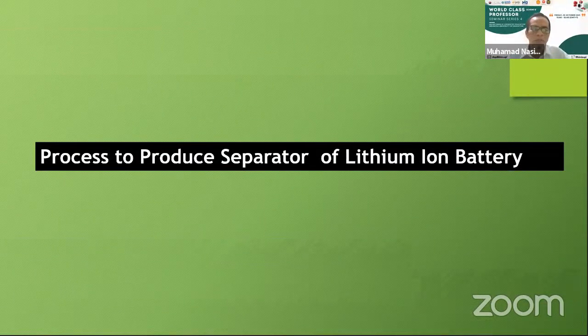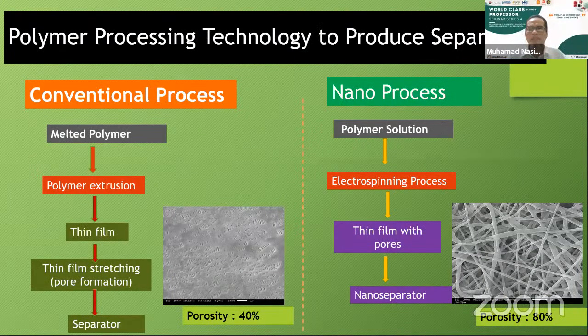Okay, we continue to produce the separator of lithium ion battery. There are two types of current process to produce the separator. You can see here there is a conventional process and a nano process. In current separators, they use the conventional process. They use melted polymer and polymer extrusion to make a thin film, and then they do thin film stretching to make pores in the thin film, and then they use it as a separator. The porosity is around 40%.